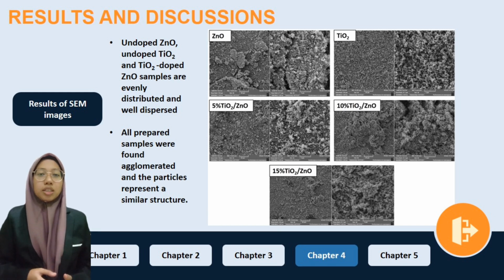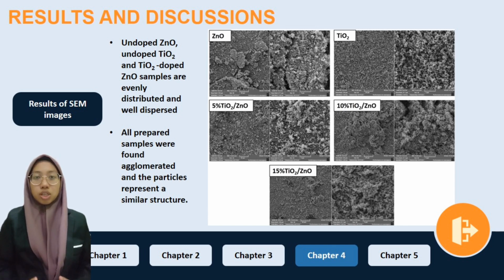In this slide, we exhibit the SEM images and morphology analysis of undoped titanium dioxide, zinc oxide, and different weights of titanium dioxide doped zinc oxide nanocomposite at magnifications of 1000 and 5000 respectively. Undoped zinc oxide and titanium dioxide doped zinc oxide samples are evenly distributed and well dispersed. Based on the observation, all prepared samples were found to agglomerate, and the particles present a similar structure.